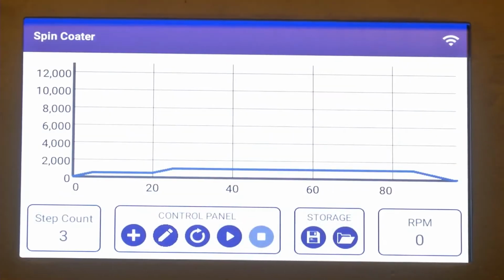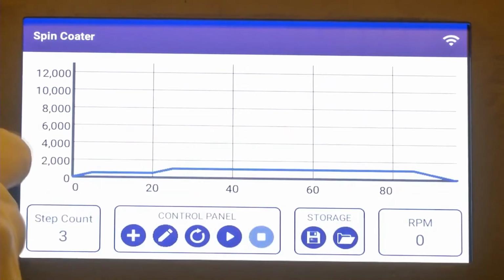So as you can see in the graph plotted, the y-axis is the RPM and the x-axis is the time in seconds. We can see there is a ramp up speed and then it stays there for some time. Then again there is a second ramp up, which is 1000 RPM. It stays there for 60 seconds or 1 minute, and then there is a ramp down. So we now have set the spin coating parameters. Let us now spin coat.